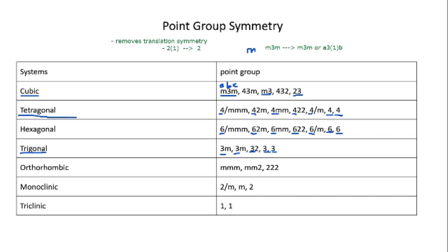So for example, let's say we have this space group P m -3, and we want to compare it to P 3 sub 1 2 1. And we have these two space groups, and you're asking, okay, which one is trigonal? So what you would do is look at both of them and see which one has a 3-fold rotation listed first, and that would be this one.